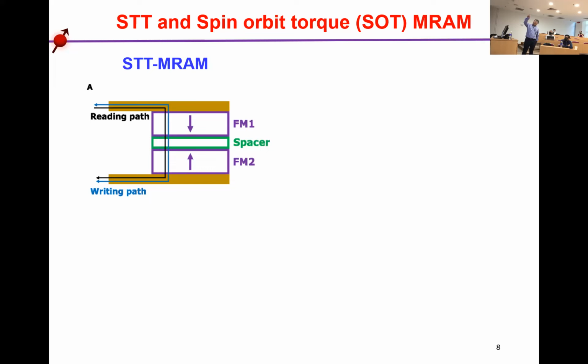In order to get the highest TMR ratio, we have to make sure the two ferromagnetic layers are anti-parallel or parallel. So in this case, there's no torque, so we cannot switch the magnetization. But when we use a large writing current, the temperature will increase and deviate the magnetization away from the parallel or anti-parallel directions. So you can use the current to induce magnetic switching.